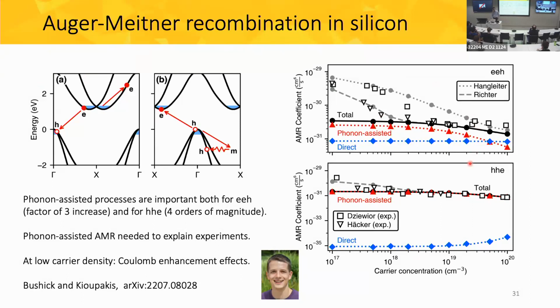The situation is even more dramatic for holes, where if we don't put in phonons, there's no state for them to go to, and the direct process is basically orders of magnitude off compared to experiment. Only once we factor in the phonons to enable the transition do we get excellent agreement with experimental data. You see some deviation at low densities because that's where we have the Coulomb enhancement effects, because you form excitons in this situation, but this can also be taken into account with models.